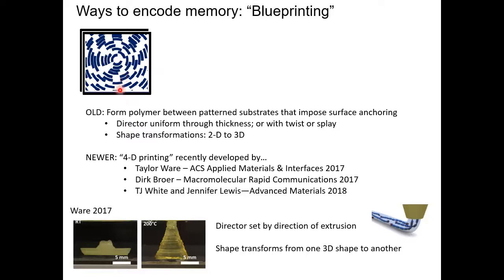Okay, then we have the cell all prepared. Then we fill the cell with liquid crystal, and we let the liquid crystal align with the pattern. Since we have the same pattern on the front and the back, if the cell isn't too thick, the liquid crystal can align uniformly through the sample with those directors. Now, mixed with the liquid crystal, we include some monomers and some cross-linking agent. Then you shine UV light through the glass and polymerize that, and you make a nice polymer that has the nematic director that you wrote on the glass inscribed in the material. And we call this blueprinting.